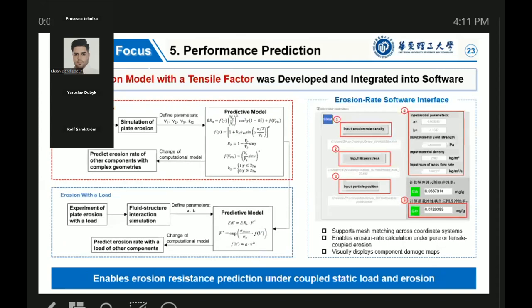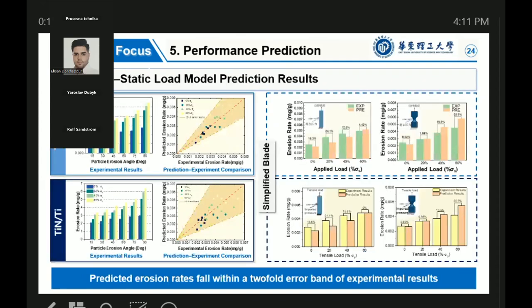We also considered axial tensile loads, which accelerate erosion damage. By introducing a tensile acceleration factor, we developed a new erosion model and software tool capable of predicting erosion performance under static load and under load-erosion coupling conditions. Also, the software accurately predicted coating erosion rates within a two-fold scatter band compared with experiments. Validation with simplified blades showed a maximum deviation of 30.9%, meeting the requirements for engineering accuracy. This enables efficient evaluation of blade life under tensile-erosion coupling.